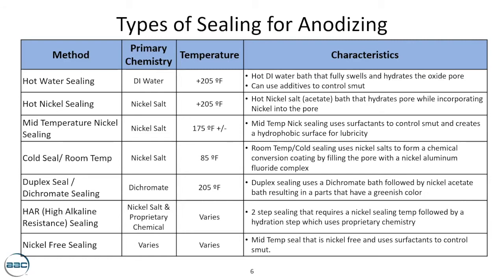High alkaline resistant sealing. This is something that's become much more popular of late, and it involves a nickel salt type of seal with a second step, which can vary in proprietary chemistry. But the intent here is to create a seal that can hold up to a 13 or a 13.5 pH. Originally, it was developed for touchless car washes to prevent a high alkaline environment where the anodic coating was being damaged. So the intent of this seal is to ensure you're going to withstand those types of high alkaline scenarios. Now, that same technology has been used and applied in the medical industry and also in the cookware industry. So it's becoming a lot more popular of late and gaining more traction in applications for industrial uses.